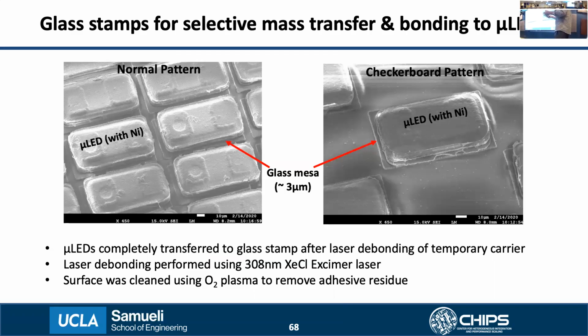These are the LEDs now fully released from the temporary carrier and sitting face up on the glass stamp, but still with the nickel stress buffer on top. So this is a normal pattern on the left and the checker pattern of LED on the right. Next, we wet etch this nickel layer so as to expose the contacts.